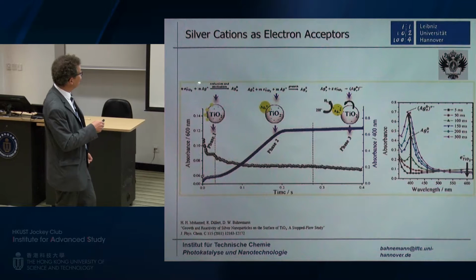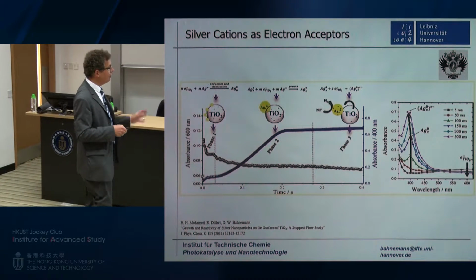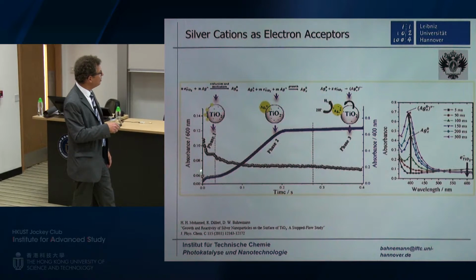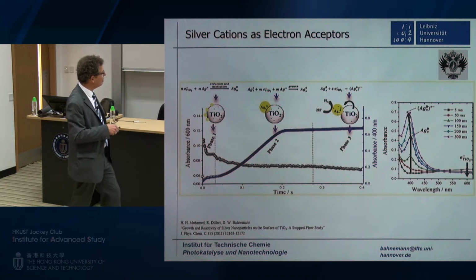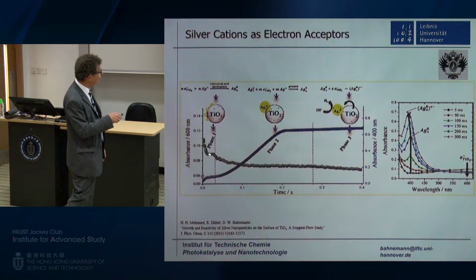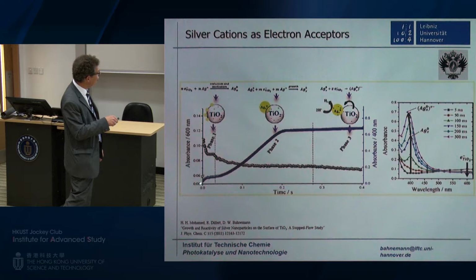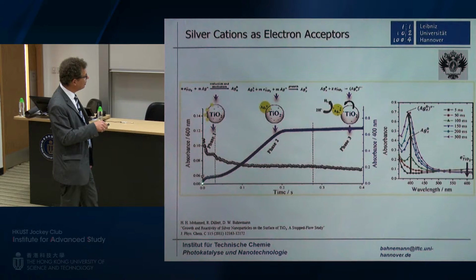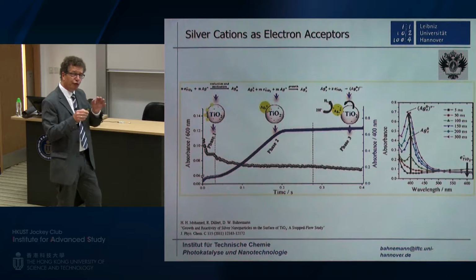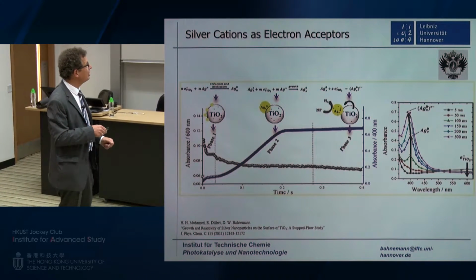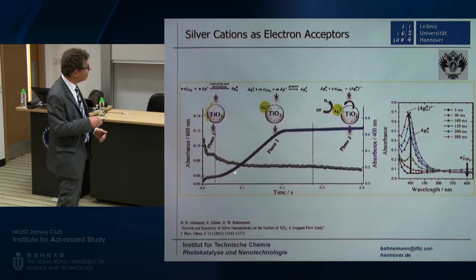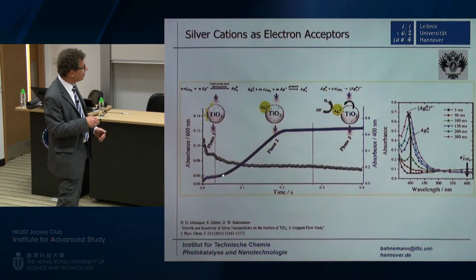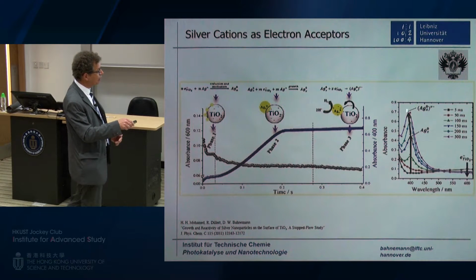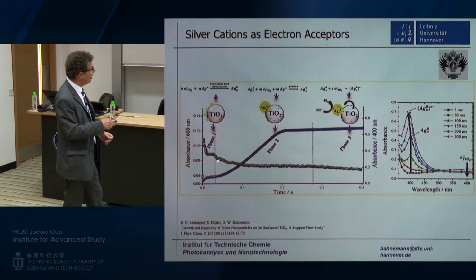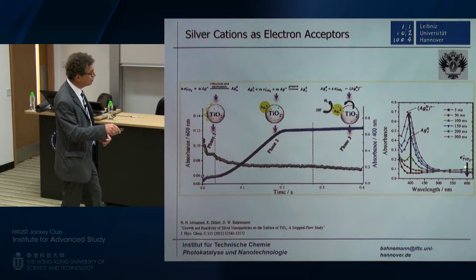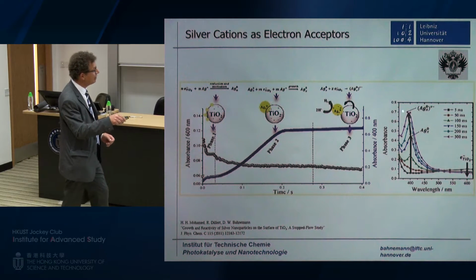Let's look at a system that I've shown you before, the system with silver cations. Now you mix these silver cations with your electrons on the TiO2, and you see quite a complicated system, but you are able to unravel the system. You first see a phase 1 where hardly anything is happening, not much absorption of the silver clusters is seen, but the electrons are consumed, and this forms the initial reduced silver atoms or clusters in the system. Then you see quite an increase of the absorption, the so-called plasmonic absorption of the silver clusters on the surface, and a little more decay of the electron absorption. So this always follows this absorption, and this follows the short wavelength absorption of the silver clusters.